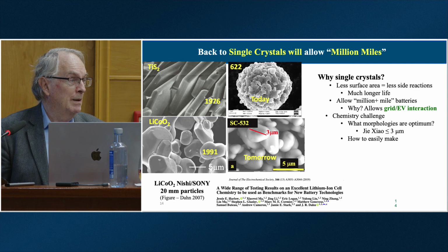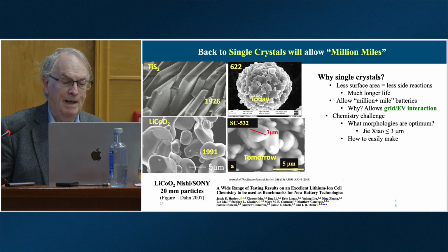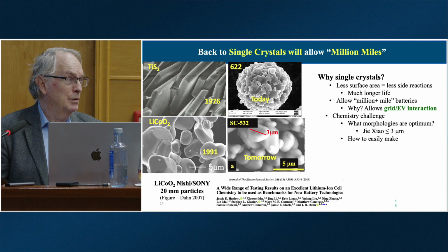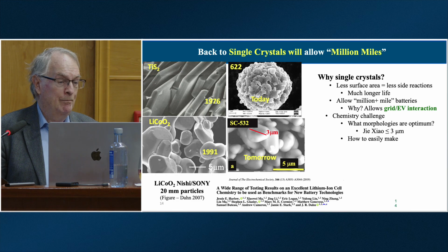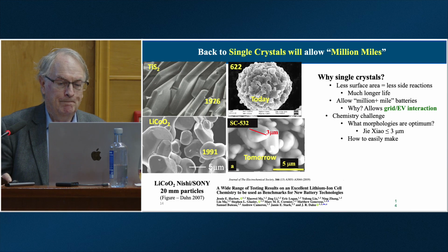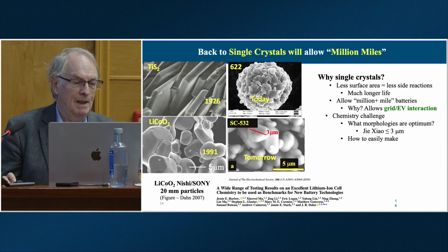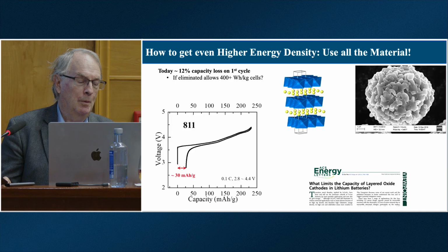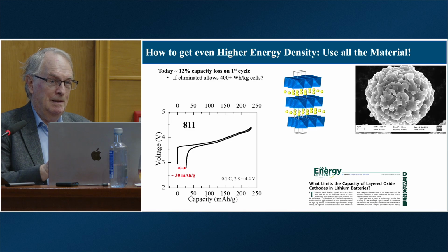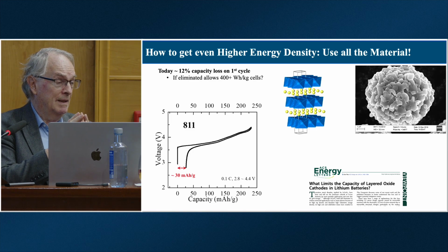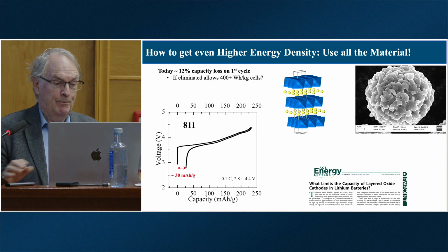What we're working on now is what's the best size of those single crystals. Say Jie Xiao, my ex-student, is saying keep them about 2 to 3 microns in size. They'll work very well, and they won't crack. I'll come back to this cracking in a moment or two. So let's first look at what we can do to increase the energy density of our present materials.